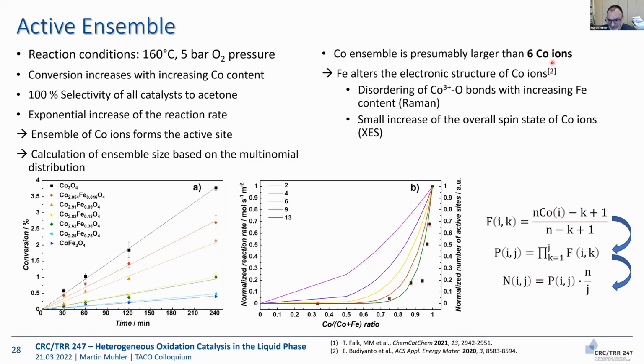Now you ask, of course, the question, what is this small amount of iron doing? And I would say we still haven't found the final answer to that question. This is, of course, now related to long-range order. What we found by measuring Raman spectroscopy, that there is a certain disordering of cobalt-oxygen bonds. And by measuring X-ray emission spectroscopy, there was some indication that we changed the overall spin state of the cobalt ions. But this is still challenging for theory now really to come up with a plausible explanation. How can this small amount of iron, when you add it, lead to this huge drop in catalytic activity? And at least for perovskites, there are some indications that the active ensemble is indeed rather large, much larger than the two cobalt ions I have shown you up to now for catalysis in the gas phase.